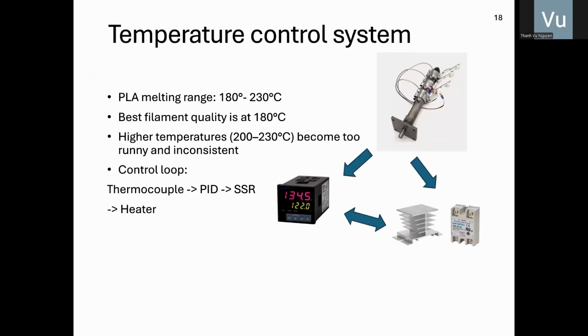Based on what we researched, we found that the PLA melting range is from 180 to 230 degrees Celsius. To determine the optimal extrusion temperature, we performed multiple tests in this range. For each test, we recorded the filament quality, flow behavior, and stability. Across all the trials, we found that 180 degrees Celsius consistently produced the best filament. At this temperature, the PLA flows smoothly but still maintains enough viscosity to form a solid, uniform, and repeatable string. As the temperature increased towards 200 to 230 degrees Celsius, the material became more watery, causing the filament to thin out, lose shape, and become inconsistent.